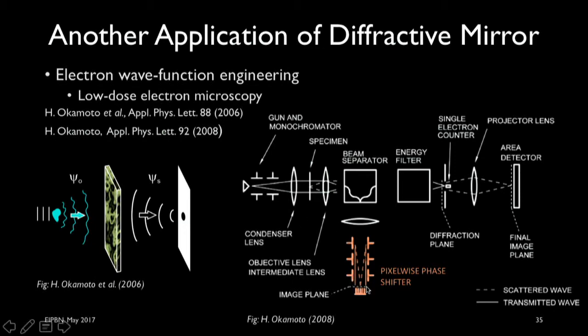So after imparting that phase shift on the electron and modifying the wave function, the electron gets reflected and gets directed towards a sample, and similar to the transmission case, if that phase shift is correct, after interaction with the sample, the electron would get focused on one spot on the detector. So again, if our guess is correct, then with a single electron, we get to know or reconfirm the structure of the sample. And if it's not the correct guess, we can dynamically change this pixel-wise phase shifter to repeat the experiment and have a second guess or more.